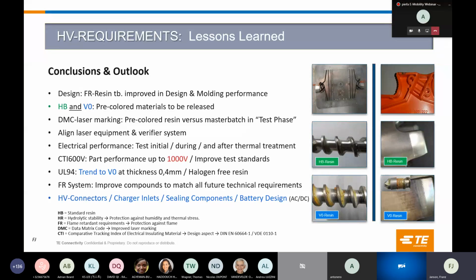Our main topic, also reflecting our needs for the part validation over lifetime, is we need to have the same performance when we produce the parts, and we need to have the same performance during the test phase and also after thermal treatment when we end the validation process. This is impossible to be achieved. Therefore, we need more participation from the resin industry to design materials which are more robust, having similar performance initially after molding in our lab, the tests which we need to do, and also what we see